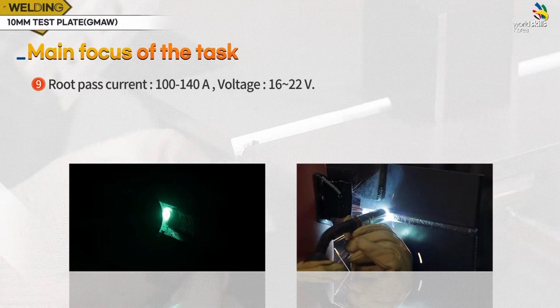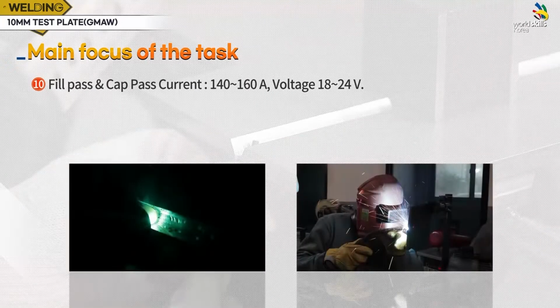Root pass current is 100 to 140 ampere and 16 to 22 voltage. Fill pass and cap pass current is 140 to 160 ampere and 18 to 24 voltage.